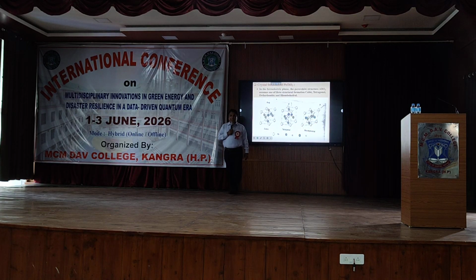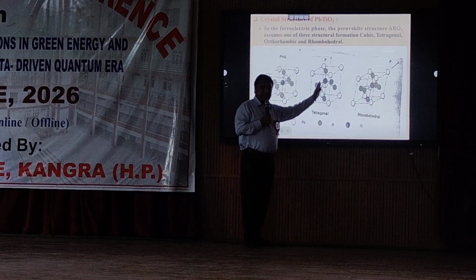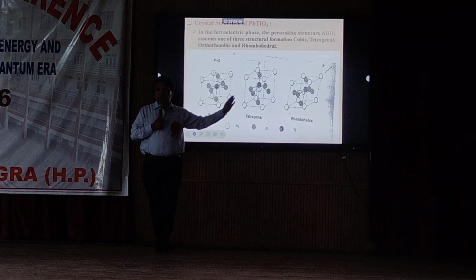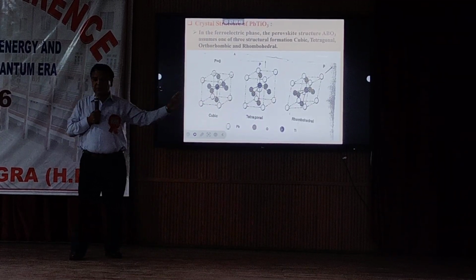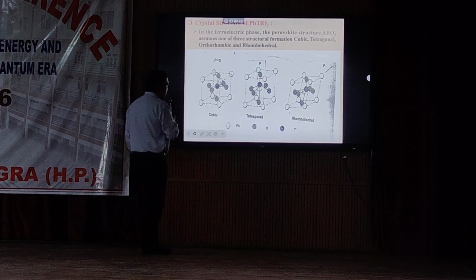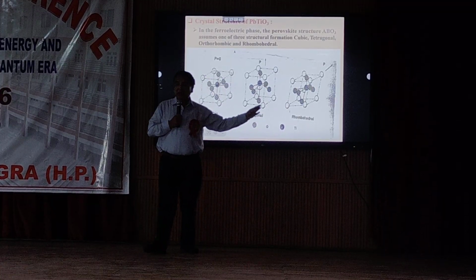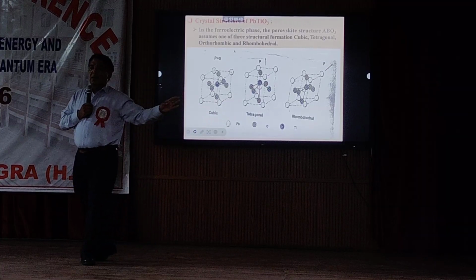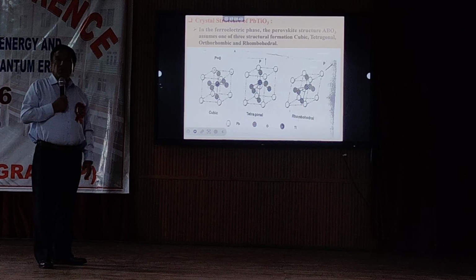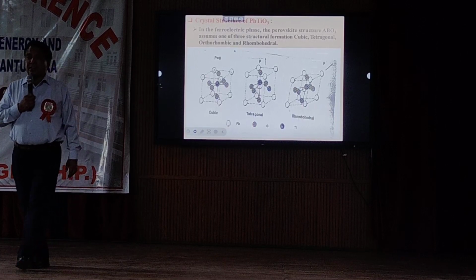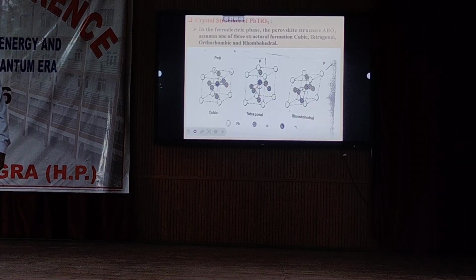In this perovskite structure material, there are three basic structure formations. The first one, if there is no distortion in the unit cell, we call cubic. If there is distortion along the C-axis, as a result of which the center of positive charge does not coincide with the center of negative charge, resulting in a dipole moment, that is tetragonal. Similarly, if there is a stretch, which I have not shown here, along the face diagonal, that we call orthorhombic. And if there is distortion along the body diagonal, we call rhombohedral. So the last three unit cell structures, tetragonal, orthorhombic and rhombohedral, have a certain dipole moment.